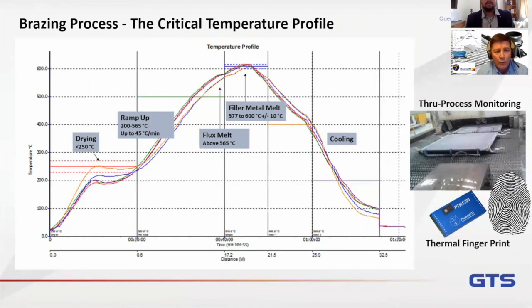The thermal mass or the loading in the furnace will be different from that in a production environment. So that's where through process temperature monitoring comes into its own, because rather than trailing a long thermocouple through the furnace itself, we're taking a data logger with multiple points of measurement, multiple thermocouples, and sending that data logger through with the product through the whole process. Obviously, we need to protect the data logger from the environment of the furnace because of the 600 degrees for the duration of the run. So we need a thermal barrier which will protect that data logger, keep it at a temperature where the measurement is still being performed accurately, and it will also protect the data logger and the thermocouples through that process.